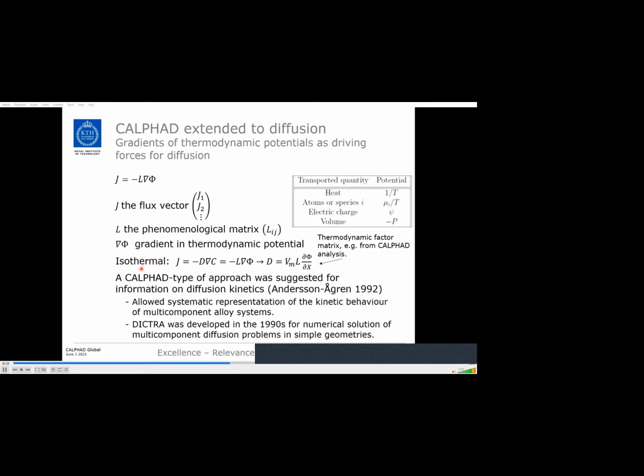So if we have isobarothermal diffusion, we can write the flux as a diffusion coefficient matrix times this gradient in composition, because that would be Fick's first law. But we know that we could also write it this way. So by making identification, we find that the diffusivity is a molar volume times a phenomenological matrix times a matrix which is only a thermodynamic quantity, and that is called the thermodynamic factor, and it can be obtained from CALPHAD analysis.